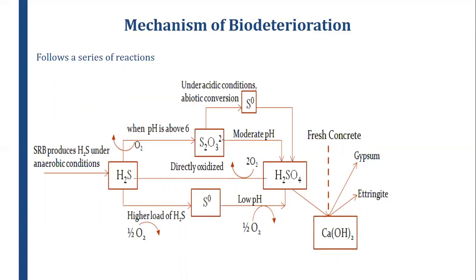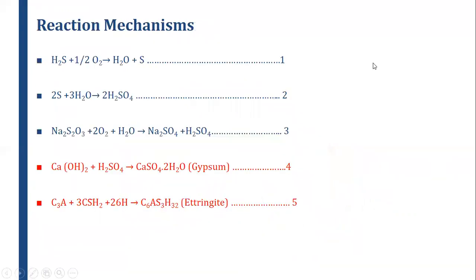Once the biogenic acid has been formed, it attacks the calcium hydroxide within the concrete matrix to form gypsum, which is an expansive material. The formed gypsum then reacts with the aluminate portions of the concrete to form ettringite. The reaction mechanisms are shown in those equations, which describe how the formed biogenic sulfuric acid attacks the cement and results in the formation of secondary materials which are deleterious.